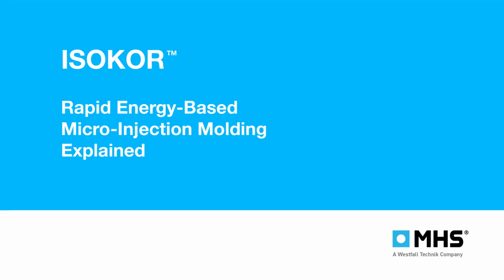Precisely. To mold a micropart in LCP, the ISOKOR process uses a valve gate open time of just 50 milliseconds. 50 milliseconds. The compressed elastic energy allows the melt to hit explosive velocities of over 10,000 millimeters per second through a microscopic 0.5 millimeter gate. It's roughly 10 times faster than the maximum injection speeds of conventional machines. 10,000 millimeters per second. That's essentially a gunshot of liquid plastic.